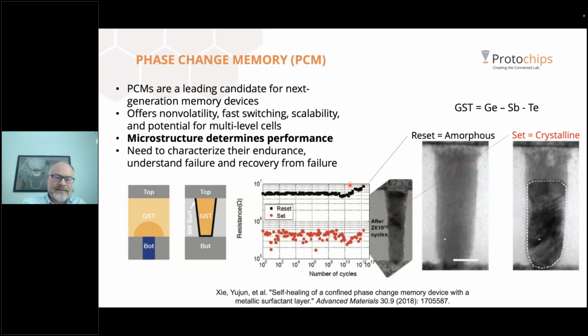It switches fast, it's scalable, and it offers the potential for multi-level cells, meaning not just 1 or 0, but multiple bits. The important thing, though, for in situ is that the microstructure of this material is what determines its performance. The resistance in the on and off state is determined by whether the phase change material is amorphous or crystalline. You have these 2 different styles here. On the left, you have this mushroom style, or you have a structure that's encased in a metal liner. And testing suggests that these devices should offer a long lifetime.